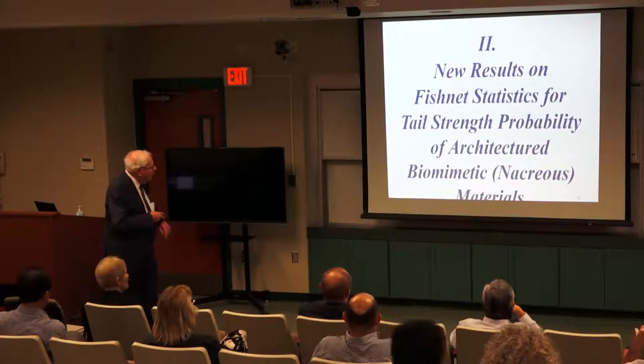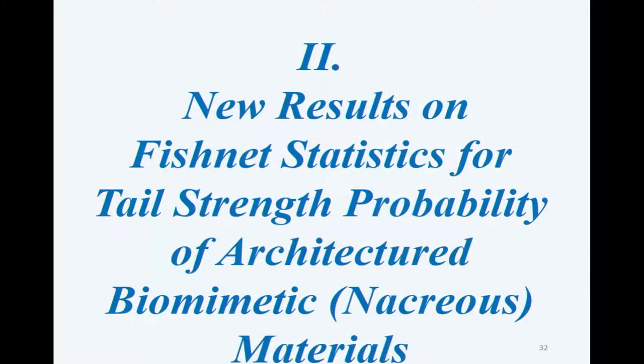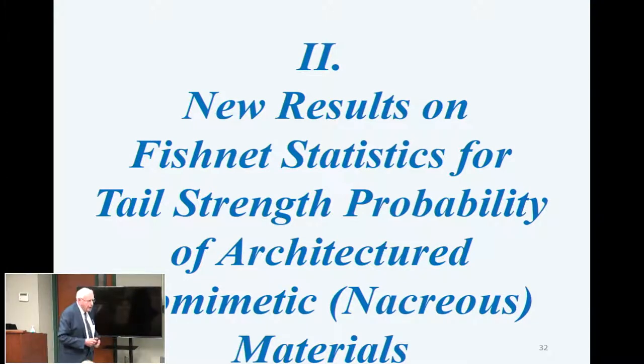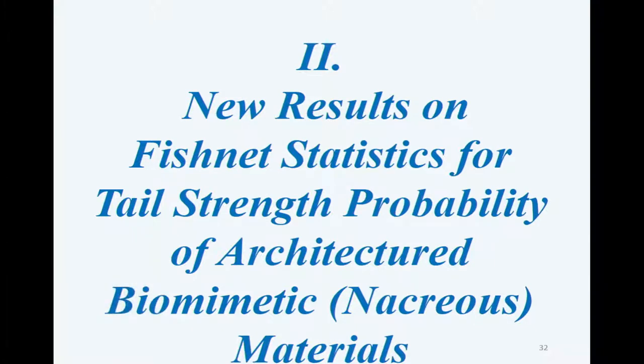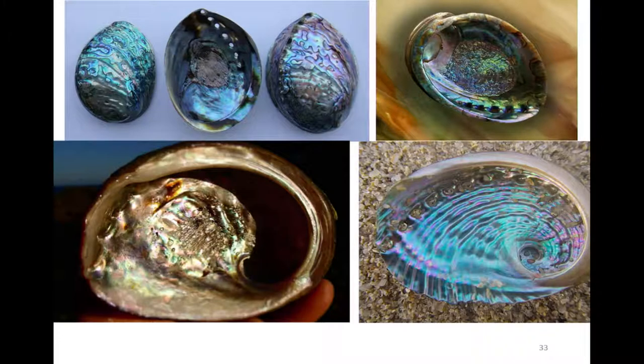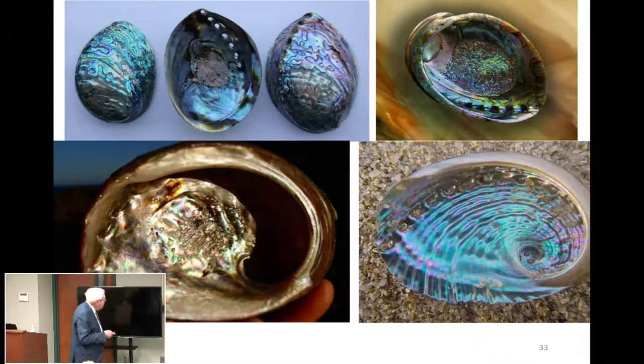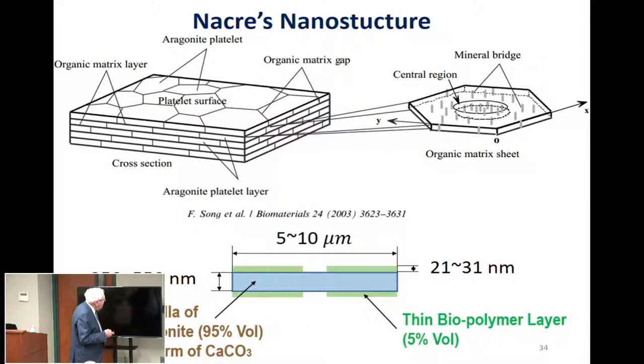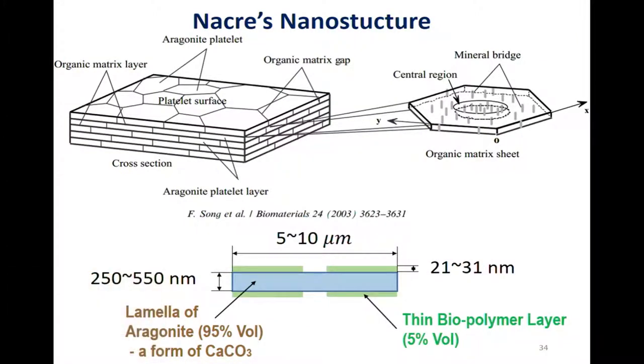So now let me get to the new result, which is not in my book, which came out 1.5 years ago. It's a result of the last about 15 months. The fishnet statistics. So the inspiration comes this way. We know that nacre, the iridescent material of the shells of abalone or some other mollusks, has extremely high strength. The strength of this material is 10 to 20 times larger than the strength of its constituents. It's mostly CaCO3, aragonite, kind of limestone.